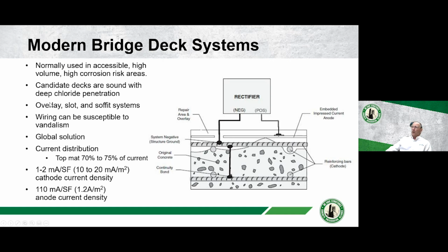In the systems that we have, there are overlays, you can do a slot system, you can do a soffit system. A soffit system is typically a conductive coating placed on the bottom, or it could be a metallized surface. You can spray zinc directly on the bottom surface of the concrete. We aren't going to talk about those types of systems today, but those can also be used as anodes to protect your deck. Wiring can be susceptible, and we have to make sure we make good wiring connections and we protect our connections.